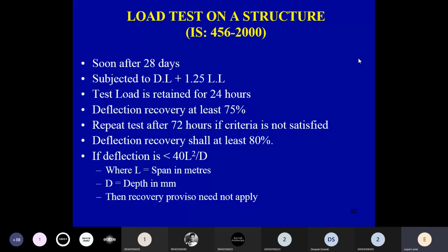By using the same principle, we apply 100% load and then we record the deflection. Once we unload the slab, if the deflection recovery is 75%, then we say that our structure is safe. But if it is not getting a recovery of 75%, then we go for a repeat test after 72 hours. Same procedure we apply, and we try to see whether this deflection recovery is at least 80% or not. This is one criterion. The second criterion is that if deflection is less than 40 L square by D, then the provision of recovery is not needed. This is for RCC. If you talk about pre-stressing, there the recovery is about 90%.